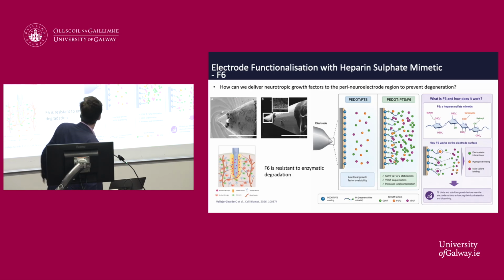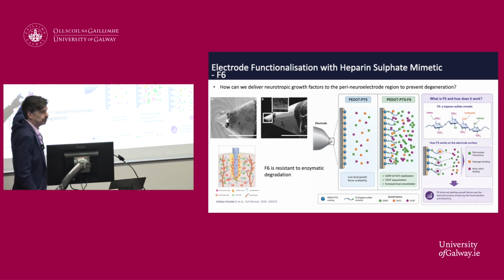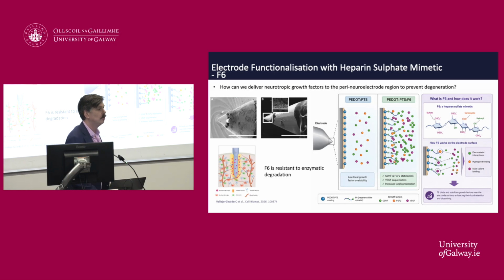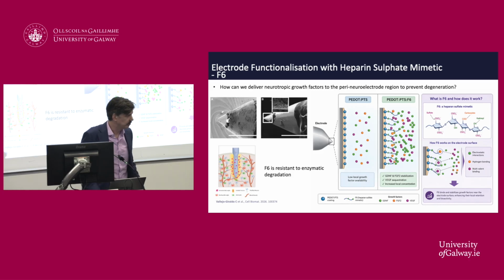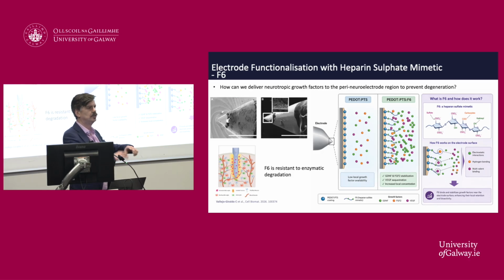So what did we do? This is what our electrodes look like under electron microscope. We took our electrodes and we coated them with a conductive polymer. So we're not using a hard material anymore, we're using a soft material because neurons prefer a soft environment. So we use a conductive polymer, a soft polymer, that we can use to coat the surface of our electrodes. But not just that, we also needed to graft a biochemistry into this polymer that was going to stabilize the environment, ensure that we don't have neuron death, ensure that we don't have activation of support cells.